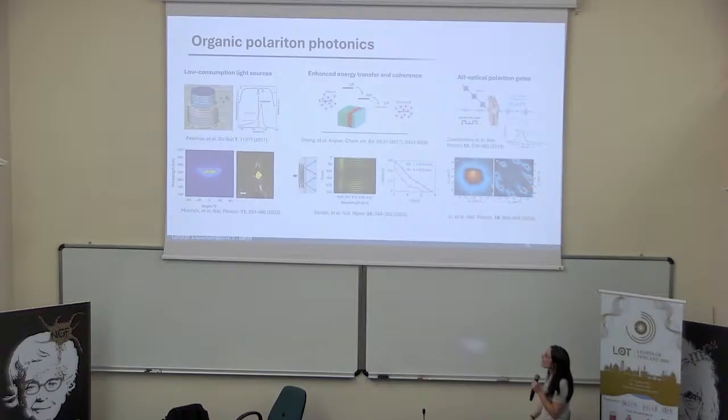There are plenty of electronic transitions, so they offer a large tunability, and so ease of applications, as I said before. In particular for polariton photonics, it is very important that organic molecules and aggregates offer large exciton binding energies, and this allows us to observe polariton features even at room temperature.